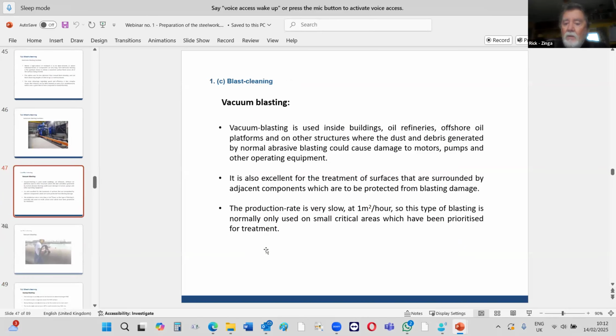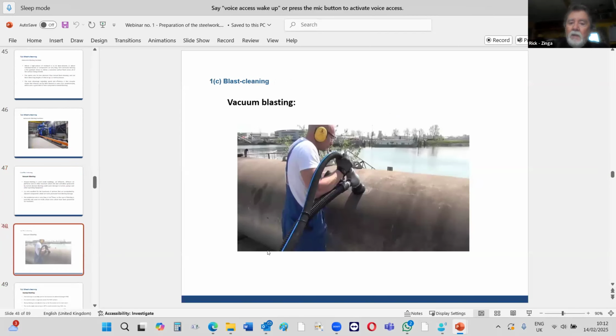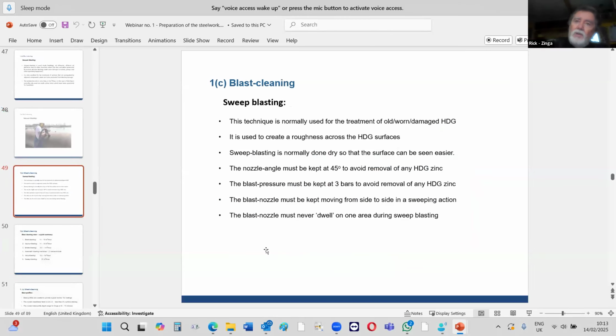Vacuum blasting again, 1 square meter an hour, like bristle blasting. But this is for inside food factories and pharmaceutical places where they need to have the area galvanized with Zinga because coatings keep failing. We said, okay, you go in with a vacuum blast, there's no mess, no dust, and you get a good profile. And again, they apply Zinga with a brush, first coat brush, second coat roller, and it comes out as smooth as a sprayed finish from a spray gun. It looks really neat. So we can offer solutions for anything in any project, literally. We don't only give answers. When they have a problem, we will give a solution.